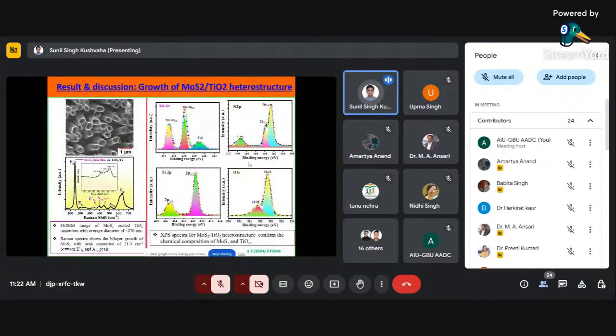So, for example, after that, we have grown this MoS2 on this TiO2 nanotube at 700 degrees Celsius. You can clearly see the change in the morphology. This MoS2 is coated outside of the TiO2 nanotube. Then again, we have performed Raman and X-ray photoelectron spectroscopy. Basically, X-ray photoelectron spectroscopy will tell you the composition and the electronic structure of your system. For example, here we can clearly see Mo is there, sulfur is there.